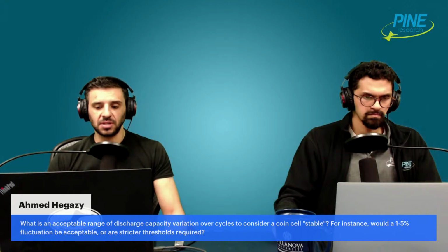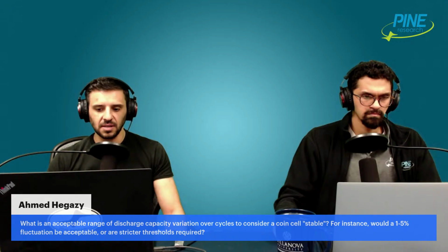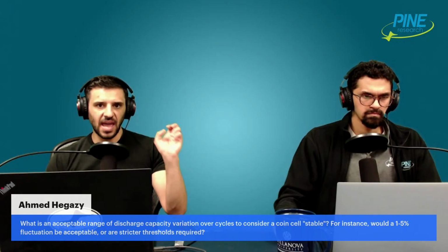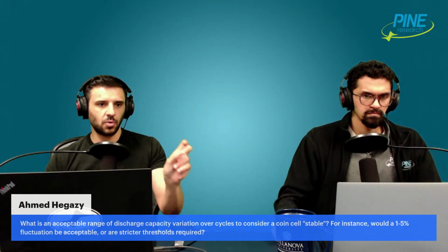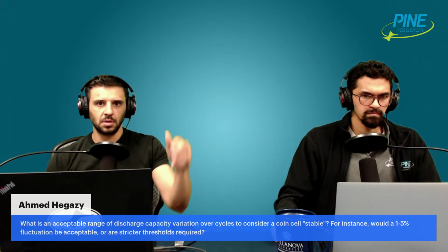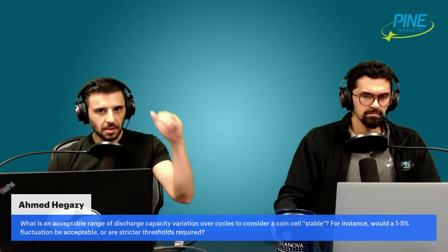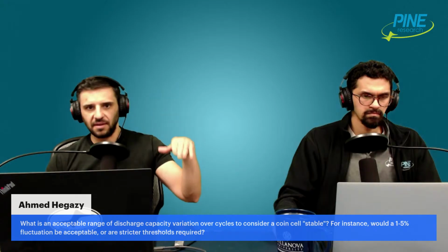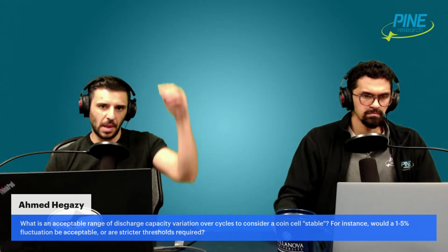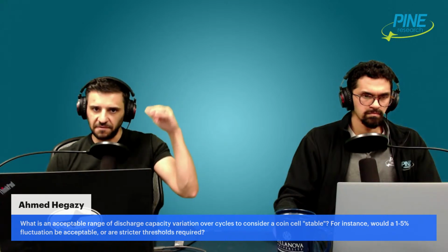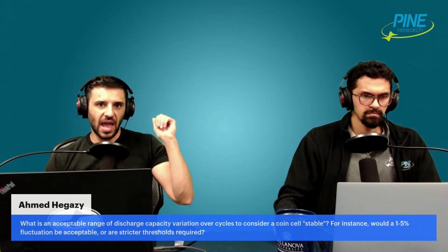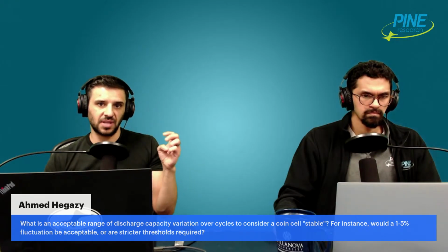So I would actually say that it should be pretty tight. I don't know that I can really give a firm number. From my experience testing coin cells, if you're doing, let's just say, 10 or 20 galvanostatic charge discharge cycles, simple, like C/5 up, C/5 down, whatever, right? Maybe there's an OCP step in between, just a very run-of-the-mill simple thing. And you're getting more than like 2 or 3% deviation.